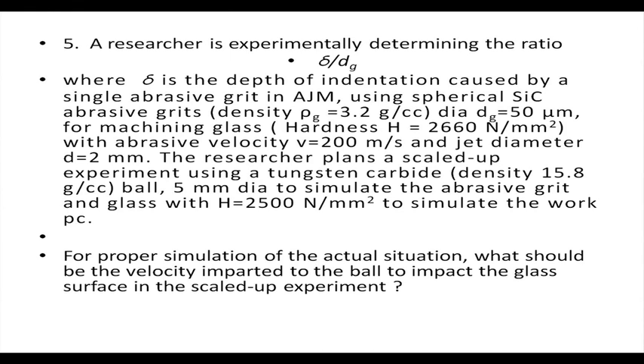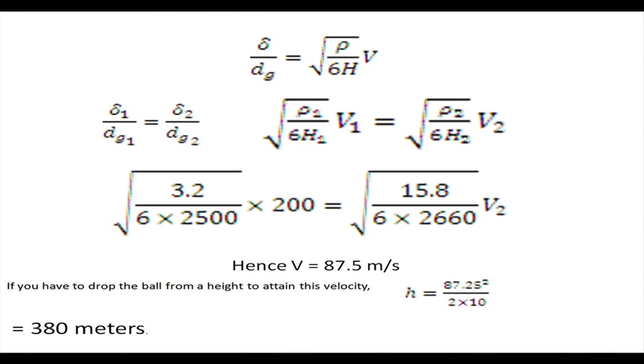I will take such a velocity such that the delta by dg will come out to be the same in the theoretical case as well as the experimental case. Delta 1 by dg1 should be equal to delta 2 by dg2. We know that delta by dg is equal to rho by 6h into v. This d is simply taken to this side. So, if this is the expression for delta by dg, let us put the values of the first case here and the second case here and say that if they are equal, what should be V2?